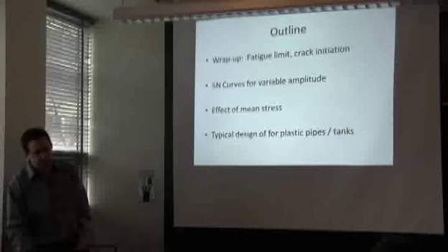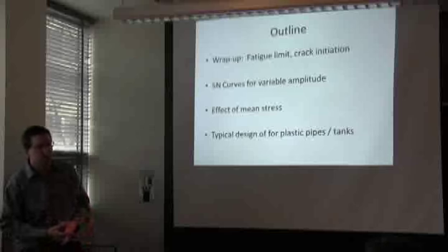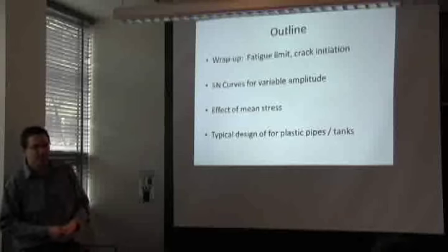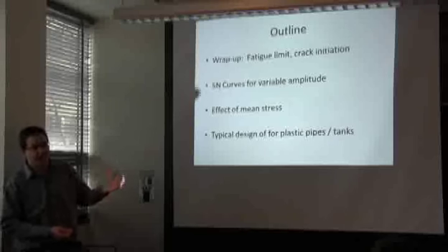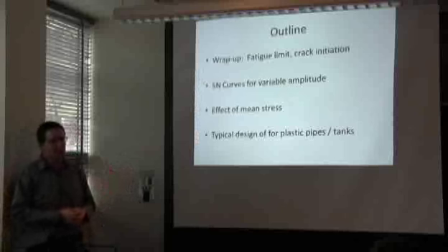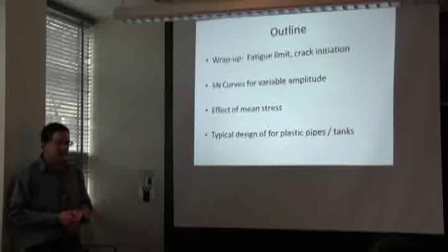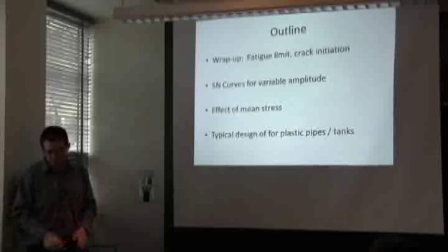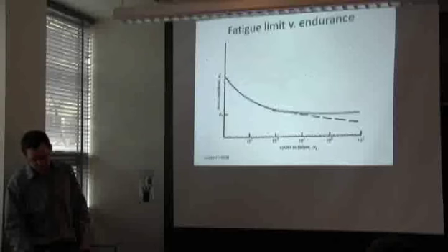So it's the same for the plastics. It's creep, but we use a very similar approach to determine whether our design is sufficient, whether we need a greater wall thickness, whether we need to derate the pipes and say, if you're going to use it with varying pressure inside the pipe, now instead of being allowed up to 200 psi, it's only going to be up to 100. Those types of conditions are part of some ASTM requirements a lot of times, that if your conditions are more severe than just a constant pressure, then you have to derate the strength of the plastic.